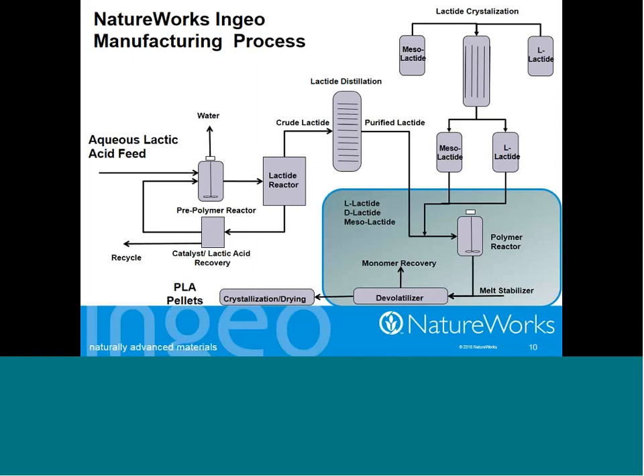This melt stabilizer arrow that we've got here is a catalyst deactivator, and that is added to prevent reformation of lactide during the monomer recovery step and also during subsequent processing by converters. We don't want the polymer chains, when they're heated up in an extruder, to head back towards the 3% equilibrium lactide that's present.